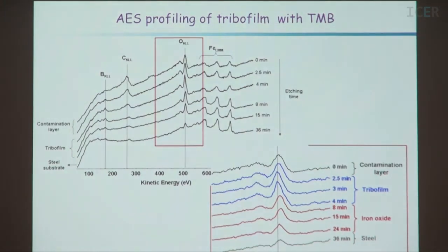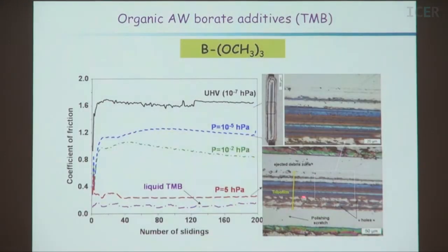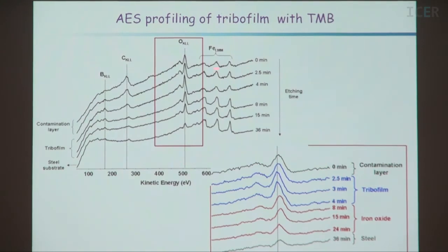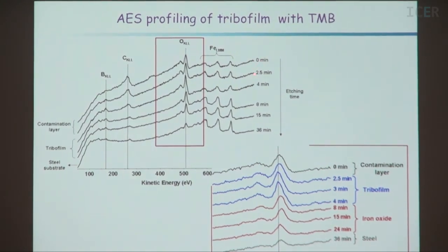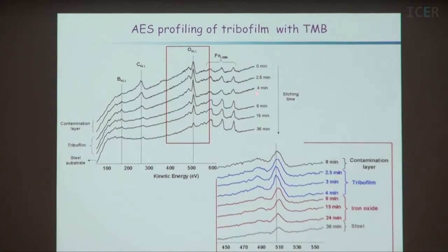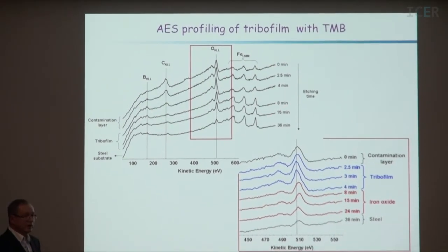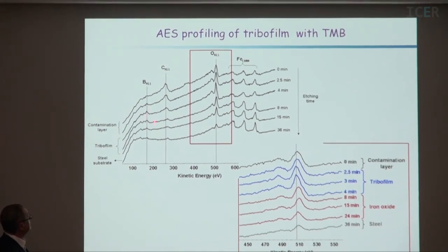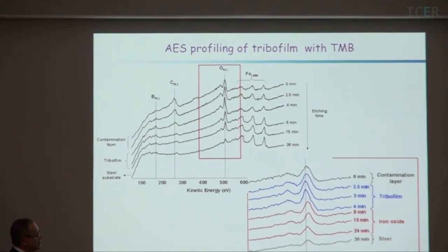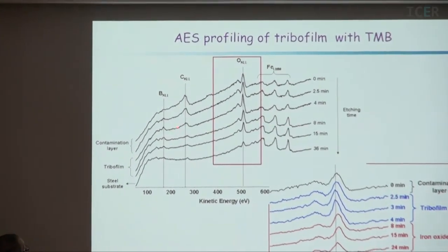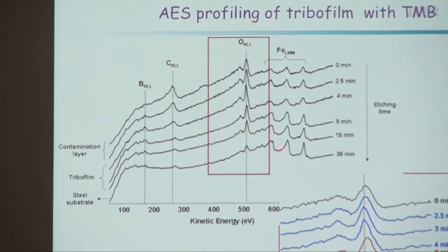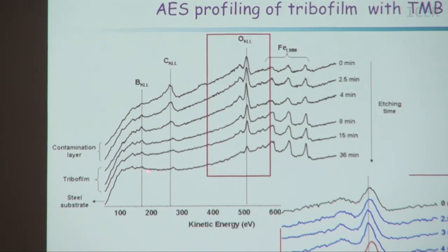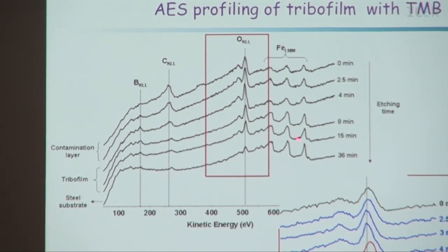So here we use Auger spectroscopy. We analyze inside the tribofilm. You can see here the surface, and here we ion etch the tribofilm to see what is inside the tribofilm. So you can see that boron is in the tribofilm, so there is a reaction of borate with the surface. And here we are now in the steel surface, so only iron is present.